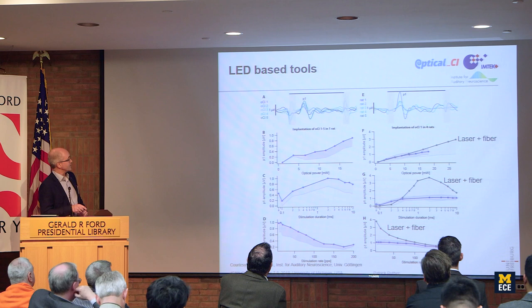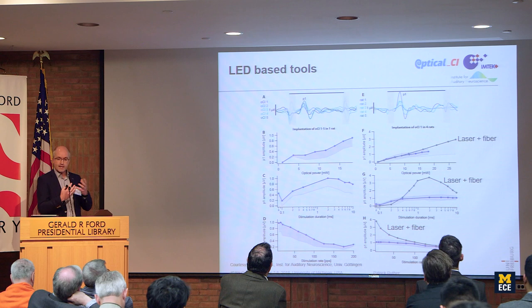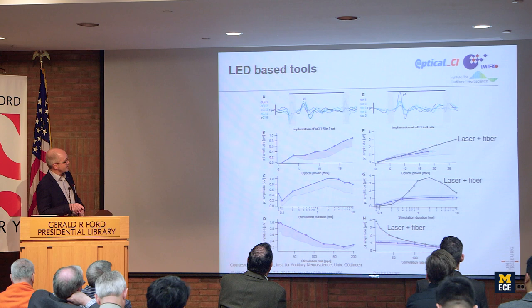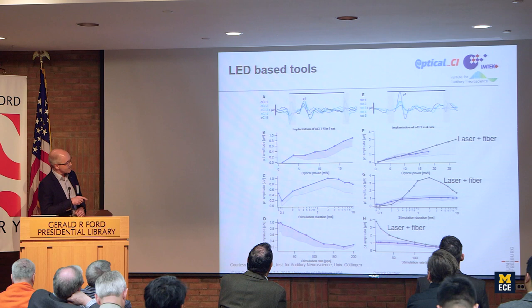we use one implant, and that is used in four different rats, showing that the system by itself is stable enough. And here we compare, in addition, the effect of the micro-LED with a laser combined with a fiber. So that is the starting point of the experiments that the group of Tobias Moser did.